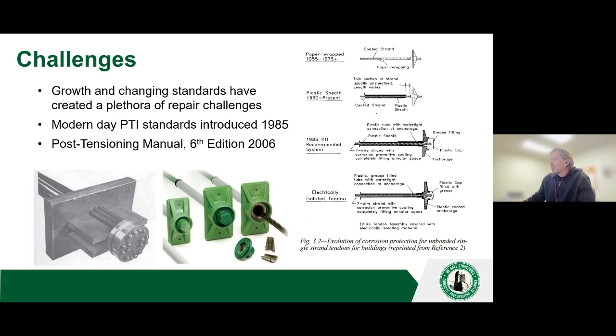One thing that I do want to note as we move forward, second from the top, the plastic sheathing, 1960 to present, you can see that sheathing was cut short of the anchorages. In my career, I've seen a number of issues with that kind of detail, and from construction practices from days ago. That can be a vulnerability when we're looking at some of the corrosion issues. In a modern structure with electrically isolated tendons, if everything is installed correctly, care is taken, typically it's pretty tough to get a significant corrosion issue going on.